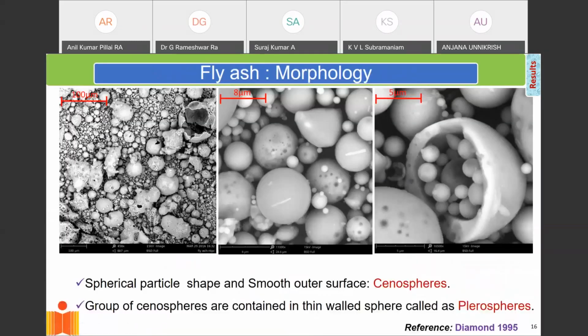And if you look at the cenospheres, more shots of the cenospheres, it is this glass content in the fly ash that we're interested in. It is that glass content in the fly ash that contains the reactive silica that we can then use when we are trying to substitute clinker, when we're trying to make cement with this fly ash.